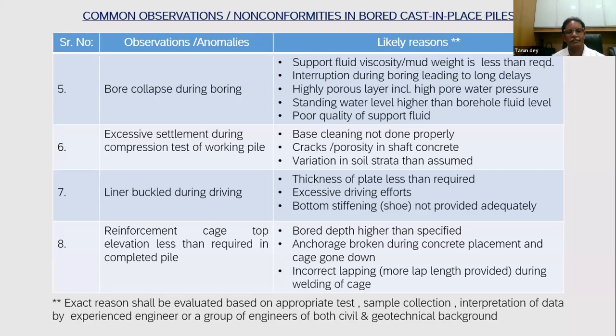Liner got buckled during driving. This is a pure case when the thickness is lower than required. When you put excessive driving efforts, a bigger hammer, higher drops. Sometimes we have seen this stiffening at the bottom. You need to put a stiffening in terms of a shoe, wrapping of additional plates, which is not provided in sufficient quantity, so you could not take the strength.